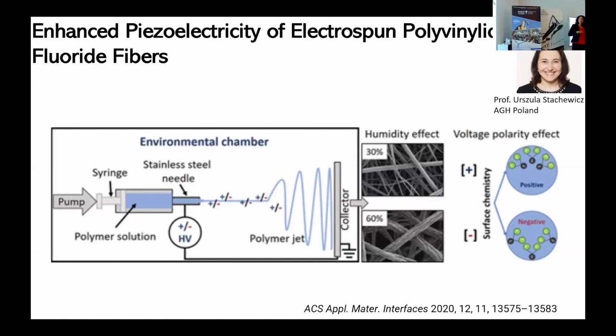We tried to look at other processing techniques and how this affects piezoelectricity. This is some work we did with my good friend Ula in Poland, who's an expert in electrospinning. This is a technique where you can make nano to micron size fibers of pretty much any polymer. The way it works is you start with a solution of the polymer through a syringe, and then you apply a very high voltage, often of the order of tens of kilovolts, between the syringe and a collector. The electrostatic repulsion, once it overcomes the surface tension at the tip, lets out this jet of the polymer, and you can use this collector to collect a mat of fibers.